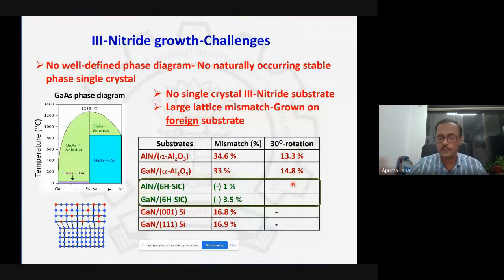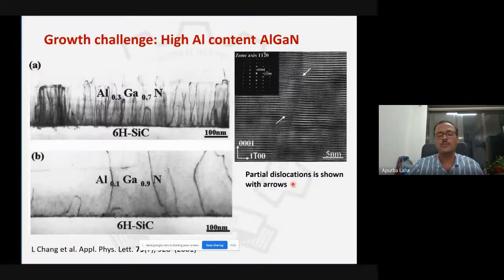Ever since the light emission was reported from this gallium nitride system, it has become very challenging. For example, despite having a very low lattice mismatch, even silicon carbide with aluminum nitride, gallium nitride, you have somewhere between 1 to 3% lattice mismatch. Now, despite having such a small lattice mismatch, the structure itself is hugely defective, full of defects.